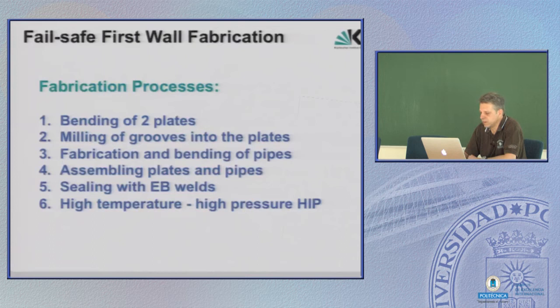And well, I think this is a rather promising idea, which has many advantages. These are the steps. You first have to bend the big massive Eurofer plates for the U-bends. Then in each of those halves you have to mill the grooves for the cooling channels. Then fabrication and bending of pipes is an industrial process. I will show you an example later. That's also easy. Assemble everything together. You can use all standard equipment. Tight sealing in vacuum with electron beam is also standard, and at the end you apply high pressure and high temperatures. So in principle this is all you need.